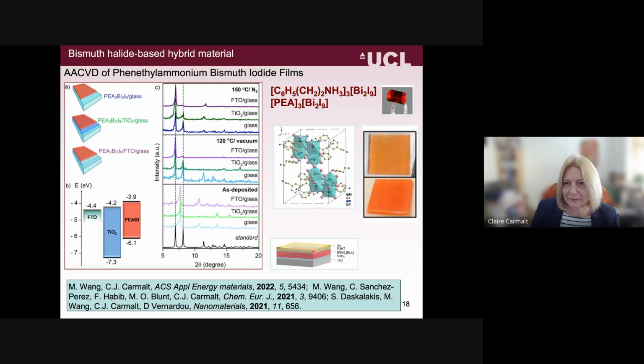We did try and make a device, but it didn't work very well. But the one thing that was very positive is that it actually shows very good moisture resistance and good ambient stability, which is largely due to the very hydrophobic nature of the cation. So it would be worth pursuing in more detail that material.